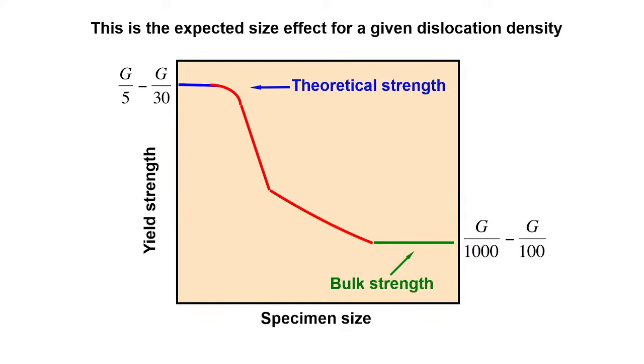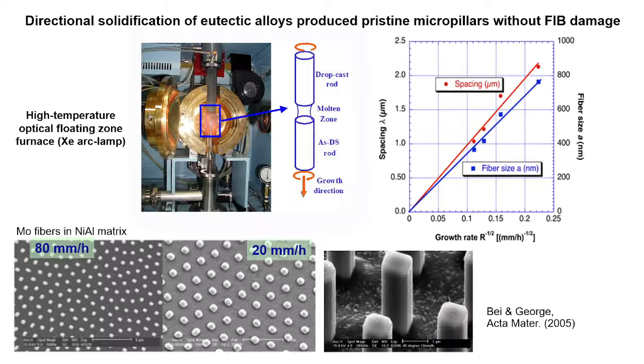And just as luck would have it, around that time, I was working on directionally solidified eutectics. And one of the systems that we were looking at was nickel aluminum with moly fibers. So these are molybdenum fibers in a nickel aluminum matrix, and we were directionally solidifying them in an optical floating zone furnace. And by changing the growth rate, right, when you grow them faster, the pillars get smaller and closely spaced. When you grow them slower, they get bigger, right?